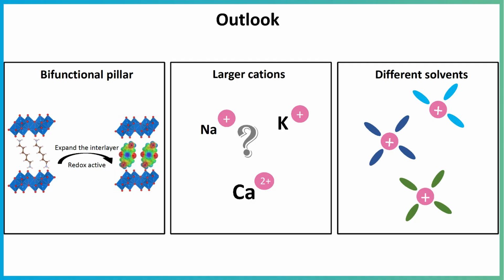So far, we used these organic pillars that are electrochemically inactive. If you think about it, they are actually dead weight in our sample. They don't participate in the charge transfer process, they're not redox active. So what we would like to do is take this study one step further, and use bifunctional pillars. Pillars that not just hold the V2O5 layers apart and change the d spacing, but are also redox active themselves, so they can take part in charge storage. And this would increase the energy density by storing more charge per gram in our cell. This would be one idea.